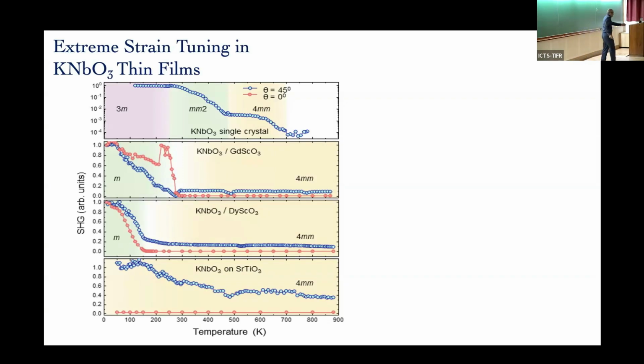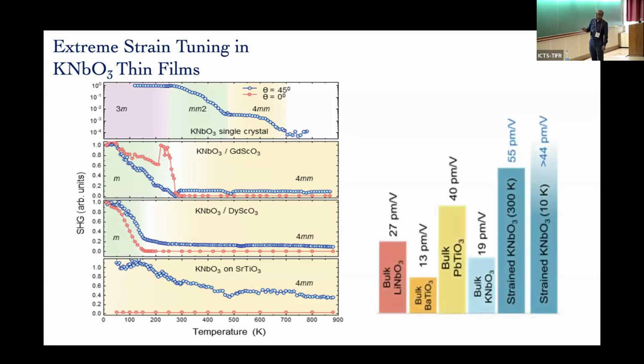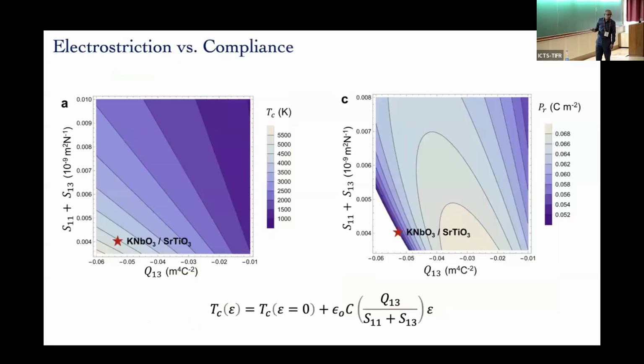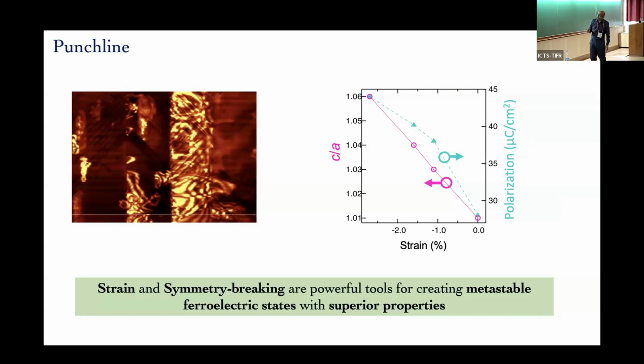Excuse me. Strain, you don't have any other phases. Okay, so just as the thermodynamic phase diagram predicts, no other phases, all pushed out at single polar phase. You can measure the optical response, that second harmonic response is huge compared to the bulk value and compared to the other compounds. All right, I'm going to skip this in the interest of time, and I'm going to say that strain and symmetry breaking are very powerful tools to create metastable ferroelectric states with superior properties.